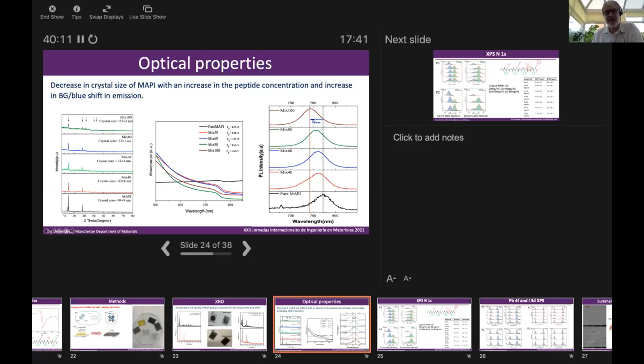The UV-vis isn't very convincing. You can't really tell properly where the onset is, but the photoluminescence is fairly clear. So these are photoluminescence spectra, excited with a broadband light source and then measuring the light that's emitted, which will give us an indication of the band gap. The black line here is the pure MAPI with the expected emission of around 775 nanometers. But as we add the peptide in, particularly when we get up to 100 mg per mil of peptide, we see about a 30 nanometer blue shift of this,